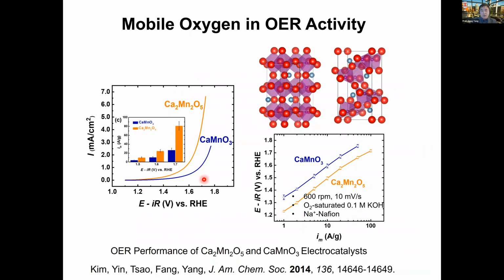So our first target compound is actually, we did a comparison study focused on the calcium manganese oxide. In this calcium manganate system, we compare the calcium manganese oxide with the perovskite. Indeed, they show activity enhancement, i.e. the Ca2Mn2O5, this oxygen deficient structure, allows the mobility of oxygen or the defect generation being favored. So you can look at both cases that work out really well.